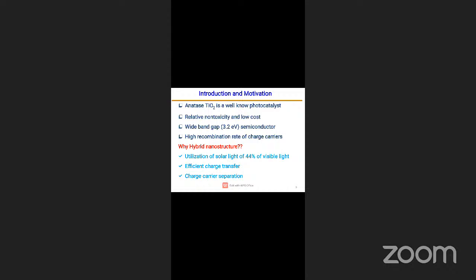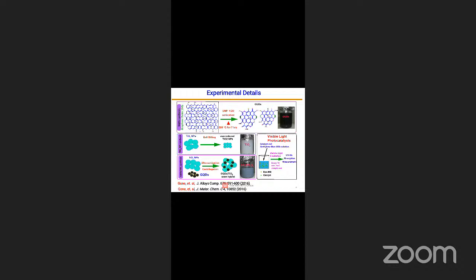And what is the utilization of this hybrid nanostructure? One is that it can utilize solar light, which has 3 to 5% UV light and 44% visible light, so we can utilize most of the visible light from the sun. One more advantage of the hybrid nanostructure is high efficient charge transfer. If you use a single material, a high recombination rate will occur, but charge can be transferred from one material to another in a hybrid. Another important point is charge carrier separation: before recombination we have to separate the carriers in order to get the free radical reactions. So I have chosen graphene quantum dots, a promising material derived from graphene.